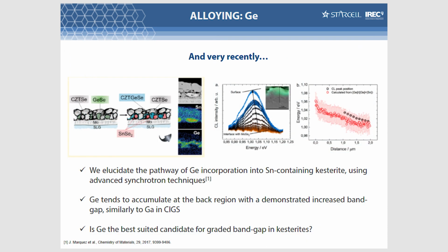And more recently, my group, collaborating with Helmholtz-Zentrum Berlin, with Susan's group, we demonstrated also that germanium not only can be used for changing your band gap, but also accumulates at the back, like gallium in copper indium gallium diselenide. So we can use germanium for advanced graded bandgap concepts, like the ones used for copper indium gallium diselenide. So germanium can be the gallium for kesterite. And this can be very relevant in the future for implementing graded bandgap concepts in this technology.